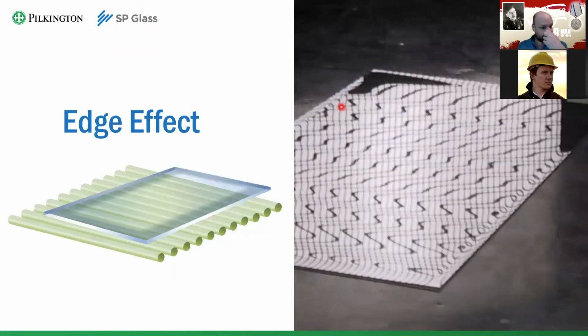Edge distortion is also an effect, but it can also be a defect if it's not done properly. This edge effect only happens on tempered glass, and again because of the tempering process. In the tempering, glass is constantly moving back and forth on the ceramic rollers, and in the process it takes some heat from them.